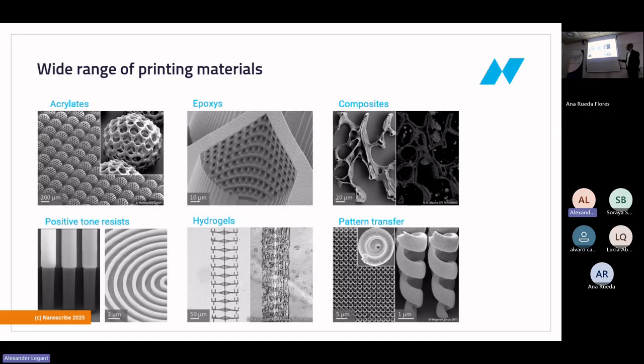Very often in life sciences, here an example for muscle cells, you work with softer materials, with hydrogels. Then you can also mix the resin with particles, so you see here some composites. And very often, and I will also show some slides about that, you start with the polymer to use it as a template. In this case, this was using electroplating to get gold structures, gold helical structures.